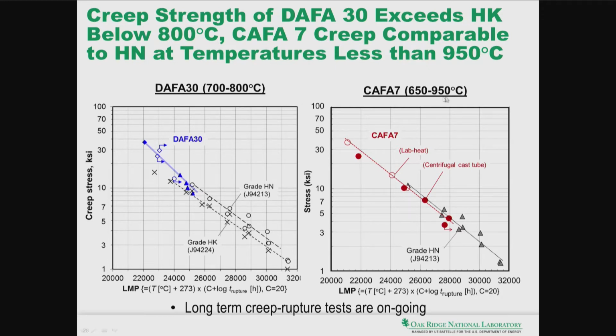The CAFA 7, with the tests running between about 650 to 950C so far. Here is the Larsen-Miller plot, and this data point that's shown with an arrow is an ongoing test with an anticipated lifetime of about 10,000 hours. But as you can see, it is performing comparable to the HN at these temperature ranges.